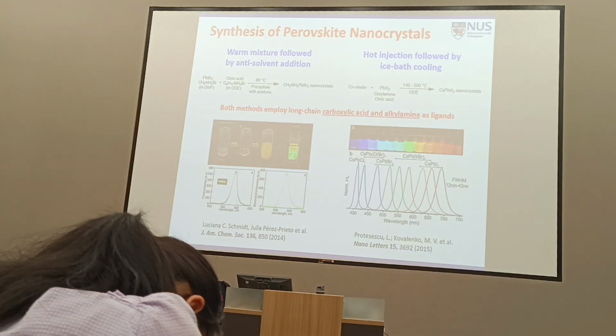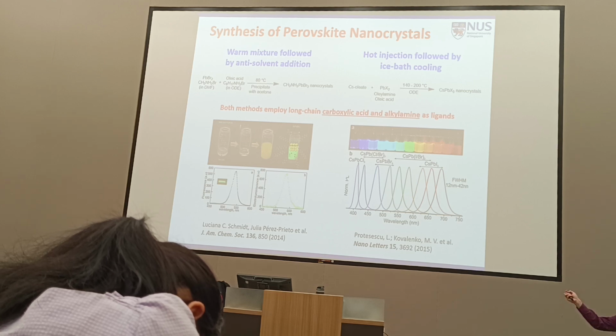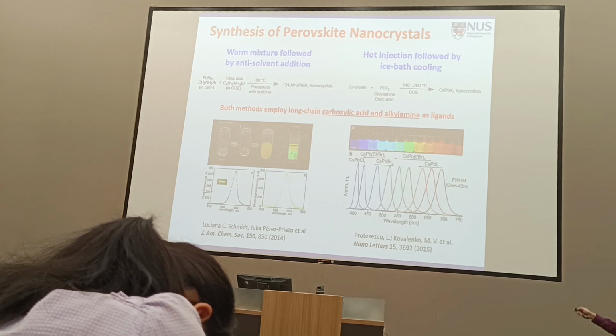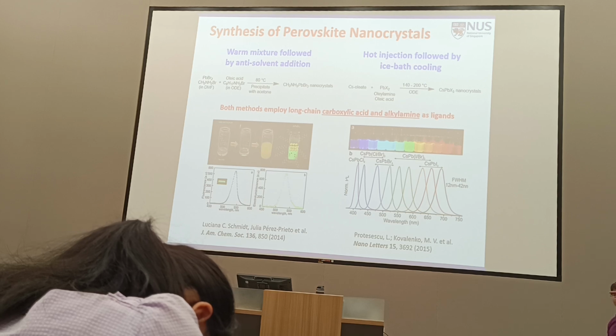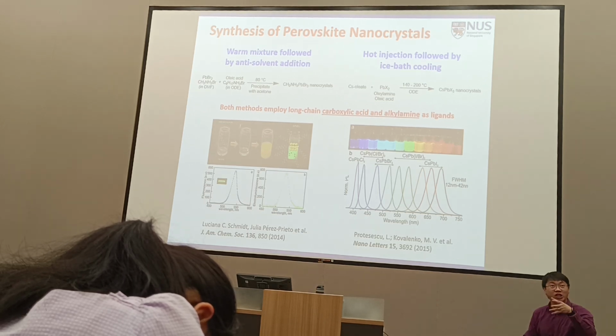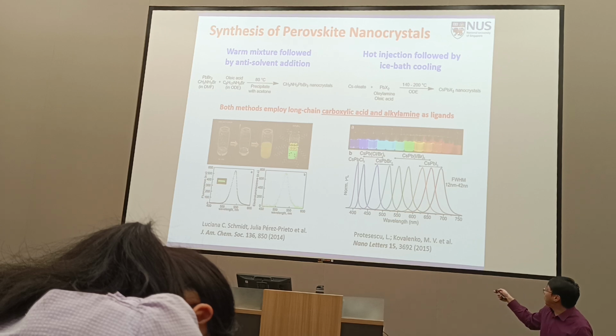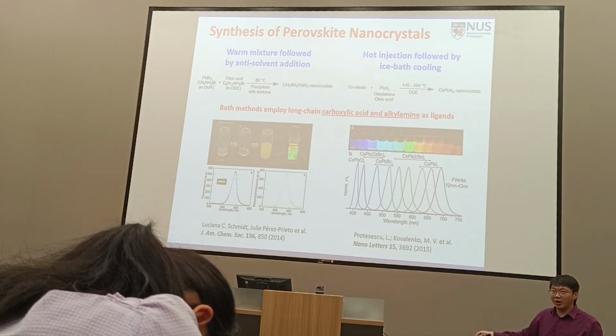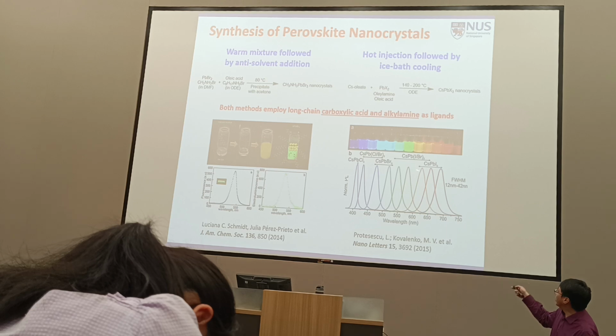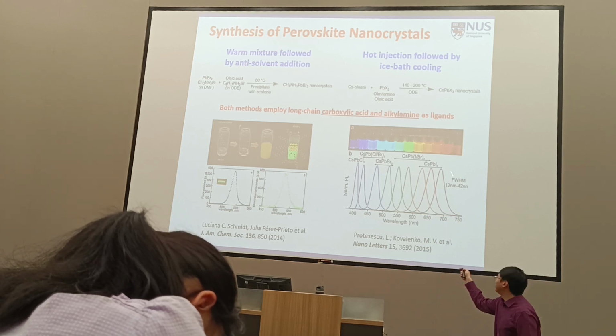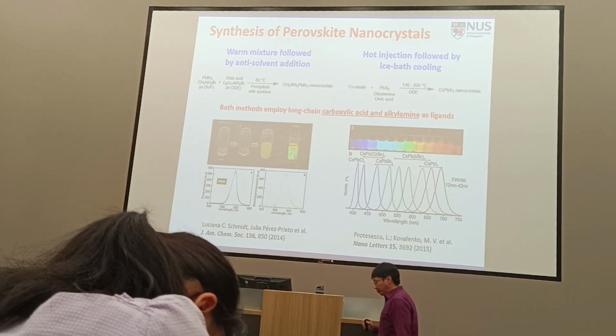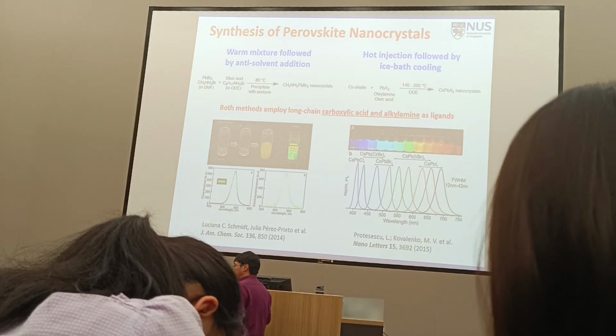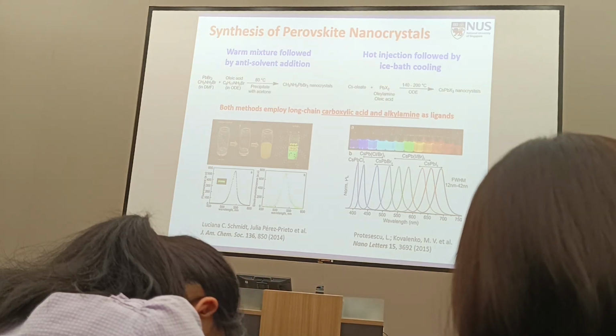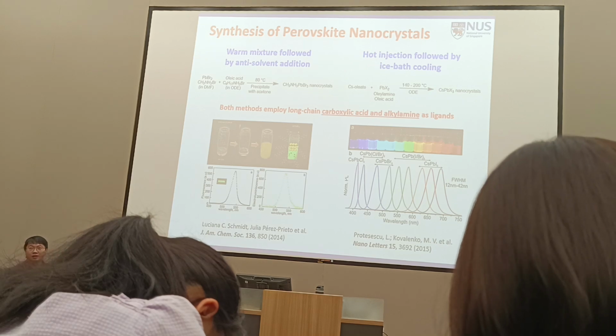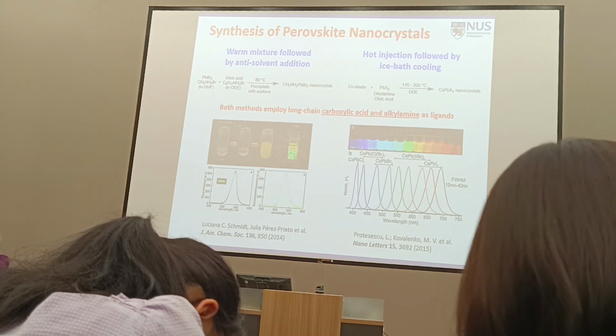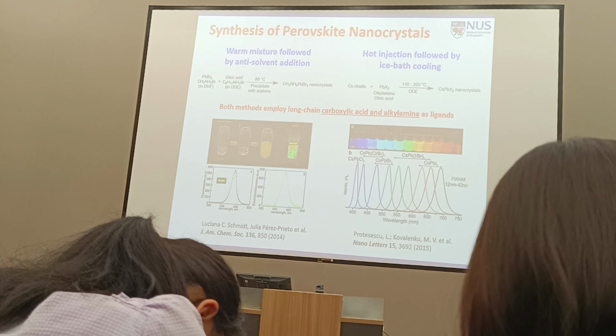One thing that they did differently is they did it with a whole range of halides. So you can see all the colors here, right? Remember, you can tune the band gap of perovskite by changing the halide. So they changed the halide from iodide to bromide to chloride or a mixture of these halides, and they got a whole range of colors. Very beautiful work. The procedures are slightly different, but it follows the same principle as what I've taught you.